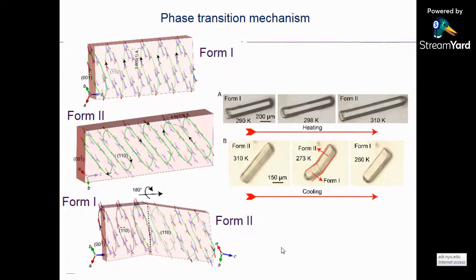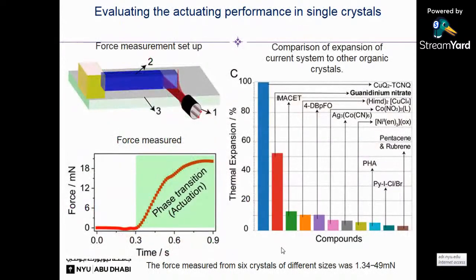These are simple guanidinium based molecules, like guanidinium nitrate molecules. In form 1, both guanidinium and nitrate are exactly on top of each other when it comes to the adjacent layers. During this phase transition, the molecules show some kind of rotation, like a 60-degree rotation we see. Due to this rotation, the crystal shows enormous expansion up to 50% of its original length. So again, as I said earlier, when you cool it, it comes back to its original shape.